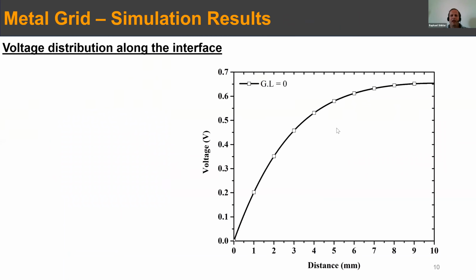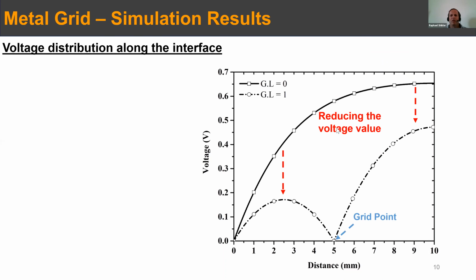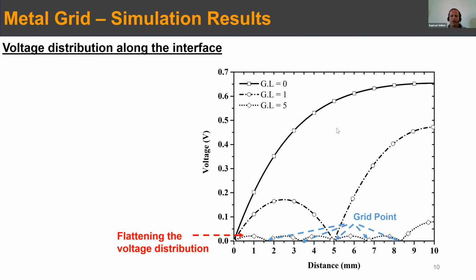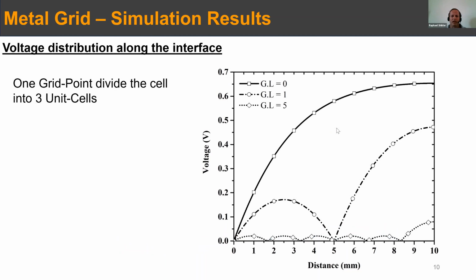Now, if we have no grid lines, then what you will get is a saturation in the voltage. If you have one point and you put it smartly across your device, then you can see that you reduce the voltage development across the anode, and therefore you increase the charge collection of the device and also the efficiency. If you add more and more points, at some point you will almost flatten the voltage distribution. Again, the question is where to put these grid lines.